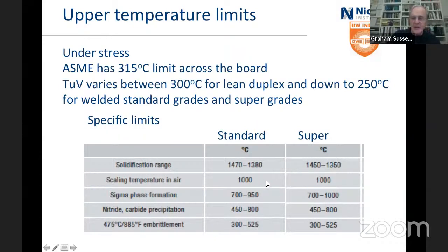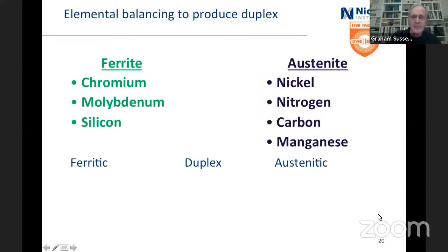Scaling temperature in air, that's basically the chromium. Sigma phase formation, about the same, although it goes up a bit further for the super duplexes because they're higher alloy. And the nitride carbide precipitation, a bit lower band, but both starting at about 450. And this 475 degree embrittlement, that's right slap bang in that range. Although you look at the curves and you think, gee, 300 is being conservative, but hey, that's what engineers are all about.